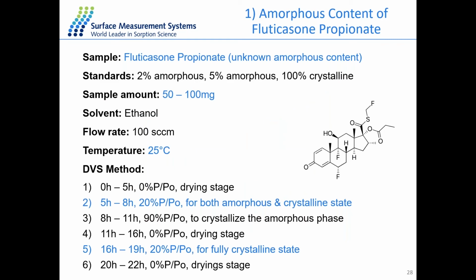So the example I have here is a fluticasone propionate sample, and we have this sample of unknown amorphous content, and we do have 3 other standards of the same nature, which are 2% amorphous, 5% amorphous, and 100% crystalline material. And to start the experiment, we first need to measure all the standard samples with the same method as we introduced previously. So we use ethanol as a crystallization solvent for the sample. We perform the experiment at 25 degrees with around 50 to 100 milligrams of the sample.